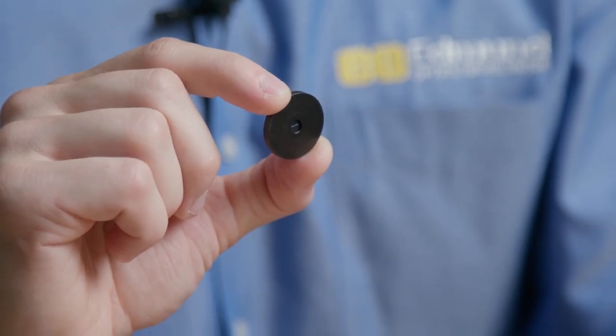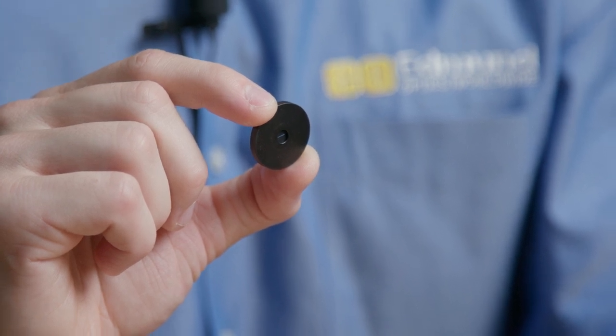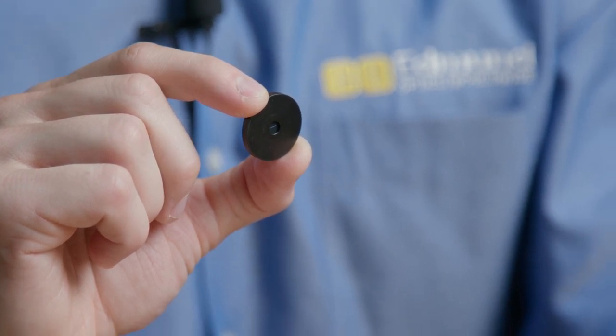Acktar Blackened Pinholes and Air Slits feature stainless steel substrates that are coated on both sides, as well as on the edges, with Magic Black. This coating provides wideband, lower reflectance from the extreme ultraviolet to the shortwave infrared, near-zero outgassing, and coating stability up to 380 degrees Celsius.